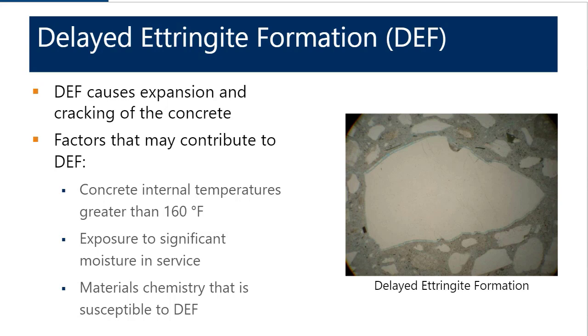Okay, our next question. When third-party testing is done on the concrete, are temperatures taken at that point? So it depends. So most specifications require the concrete to be sampled at the point of placement. And then as a result, the temperatures will then be taken at the point of placement. Sometimes the concrete is sampled at the truck.